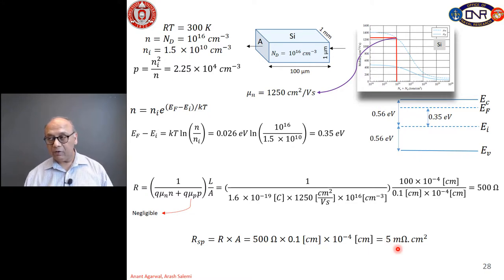What this means, and this is very often used for power devices, and we'll use this later on, so it's good to describe the concept here. If we could have a semiconductor with 1 centimeter square cross section, then the resistance of that slab would be 5 milliohms. If we reduce the area, then the resistance goes up. If we increase the area, then the resistance goes down. But this basically means if we have 1 centimeter square cross-sectional area, then the resistance is 5 milliohms. So that's the definition of specific on resistance: it's basically the resistance times the cross-sectional area. And this gives us a basis for comparing different materials. If they have different mobilities for electrons and holes, then we could say this has a higher specific on resistance than the other material.